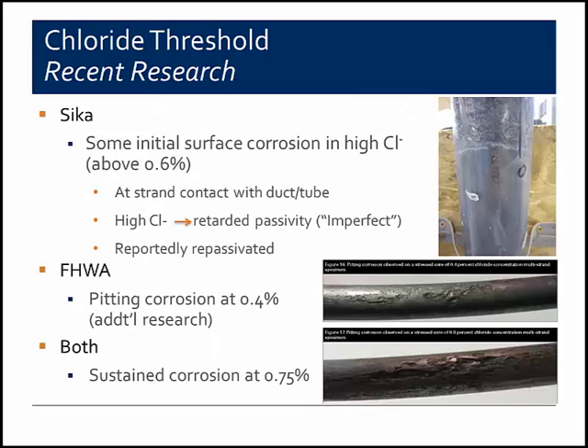And so, some of the initial results that have been reported: in Sika's research, there was some initial surface corrosion found in some of the samples that contained high chloride content, and I say high by 0.6% and above, with it being more noticeable, obviously, in the higher chloride samples. And these local corrosion conditions were generally at the point where the strand was in contact with the duct, and the theory was that the high chloride had retarded the passivation of the strand, particularly where it was not encapsulated in grout, and instead it was in contact with the plastic tube.